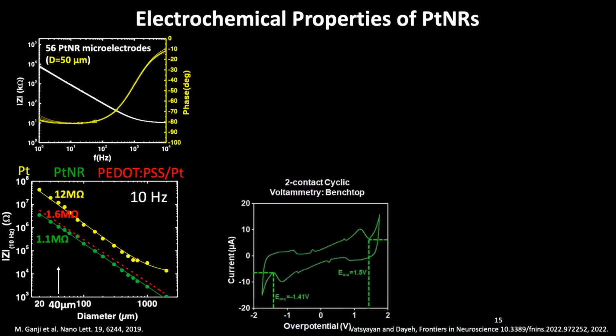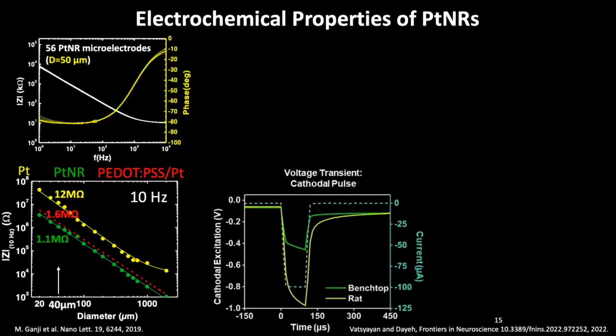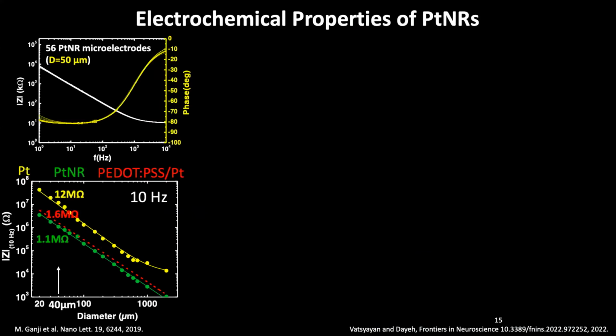We start with cyclic voltammetry, in which we expose the electrode to potentials and look at the current surges. Those current surge regimes, for example, on the right would be the regime where we start to have oxidation, when we start to have hydrogen bubbles on the left, and those would be the limits for electrolysis across the electrode tissue interface. And then we start pulsing the electrode with different current pulses and estimating the potential drop across that electrode interface that we talked about, the half nanometer or so, both in benchtop and in vivo settings.